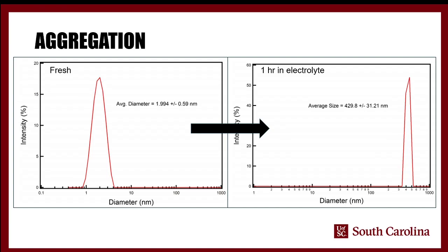And basically, what happens is when you add both the tripropylamine and the supporting electrolyte, the tetrabutyl ammonium hexafluorophosphate, you reduce, because the propane thiol ligand is not charged, the repelling force is not very strong, and so as soon as you add a supporting electrolyte that can provide even a little bit of ionization, the particles are going to want to come together, and so you end up with, again, an aggregate. It's a stable aggregate, but it's an aggregate nonetheless.